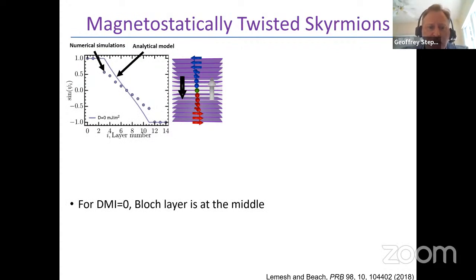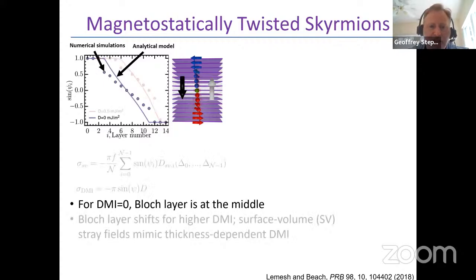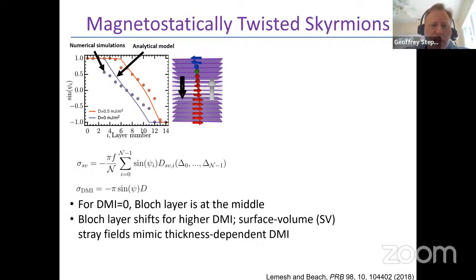So if one has a magnetic multilayer in which there is no DMI, the closure stray fields will lead to Néel textures at the top and the bottom. And right near the middle of the stack, the structure will be Bloch. As one adds DMI to the film that prefers one handedness versus the other for the Néel texture, that will tend to push this node towards one of the interfaces. So more and more of the layers become Néel with a particular handedness, and one can compute this.